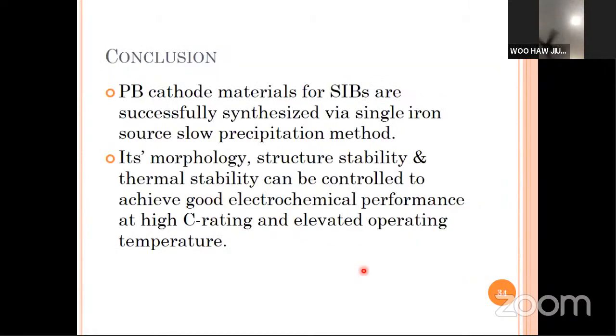This is the conclusion. Prussian blue cathode materials for sodium-ion batteries are successfully synthesized via this single iron source slow precipitation method. And its morphology, structure stability, and thermal stability can be controlled to achieve good electrochemical performance at high C rating and also elevated operating temperature.